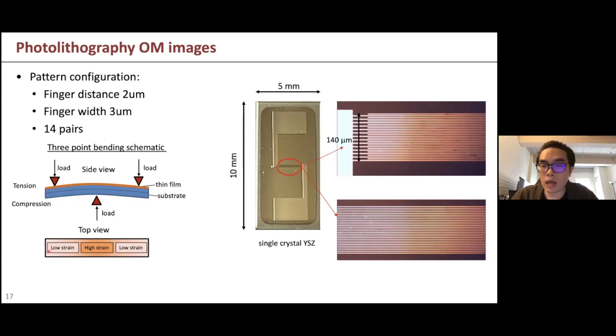And if we look at the top view, the strain is also not the same in the XY direction. It is the highest where you have the loading point, and it is zero where you are closing to the supporting point. So if we want to use three-point bending and measure the conductivity change with respect to one strain value, we have to make sure that it does not really cross a very large region.